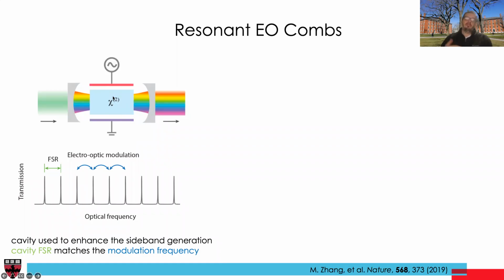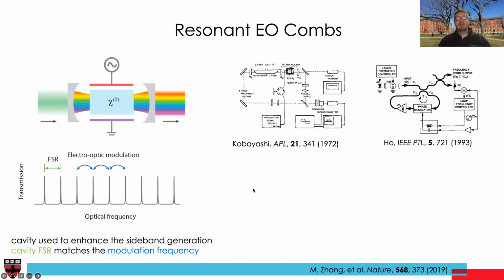And then we made this a little more complex. We took one amplitude modulator and one phase modulator, plus this chirped grating for compression. But in reality, the process can be made a lot more efficient if you take a phase modulator and put it in an optical cavity. The free spectral range of this cavity is the same as the modulation frequency that you're applying, the RF frequency. This process of sideband generation is resonant with the cavity, and thus it's enhanced. And then you need less optical power or less RF power to generate a very broad comb. That has been done